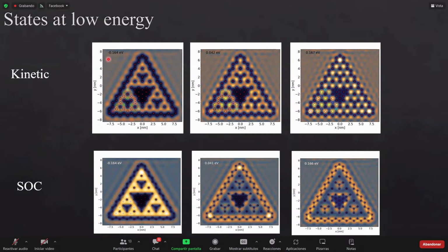Thank you a lot for the presence and also for the question. The important point here is that, for us, the spin-orbit coupling will act, as I mentioned, as a kind of artificial magnetic field for different spins. It will make the circulation of the states and the presence of states localized at the edges that are related to the topological features of the system. In the first row here, I'm showing the states without the spin-orbit coupling. They are interesting by themselves, since you can see the properties of this fractal structure, but you don't see any states localized at the edges or corners of the system. So you need spin-orbit coupling to see these states. That's what we want to model in the experiments.